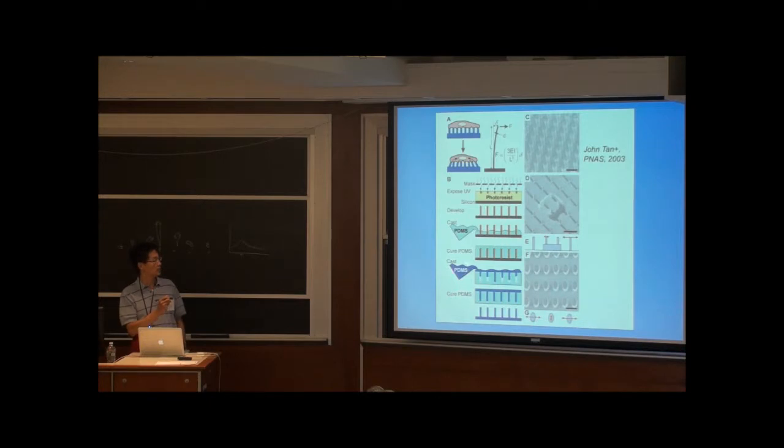And then we pour another layer of silicone into these holes, and once that polymerizes, you can peel that off and you're left with basically this substrate now in an elastomer, something that's linear elastic, okay? So with this, you can generate all kinds of patterns.